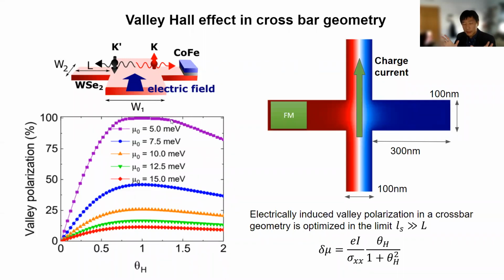And you can understand this by looking at the two bands. This Fermi level is measured with respect to the band edge of the material. So when you are closer to the band edge, it's much easier to deplete one valley over the other valley. If you are able to deplete the electrons in the other valley completely, then you get 100% spin polarization. So that's basically the reason why for low doping it is much easier to deplete one of the valleys.